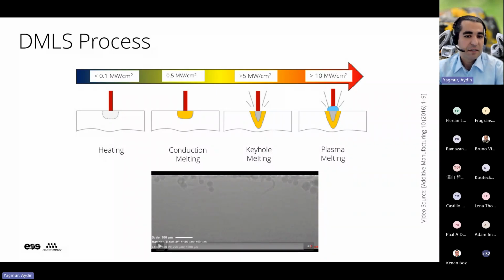And the second reason is with keyhole melting, due to the deep, narrow shape of the melt pool, we can get better interlayer cohesion. So the connection between the layers is better. And due to the narrow shape, the absorption of the laser beam is better, so laser efficiency is higher. That is why we rely on keyhole melting in our technology.